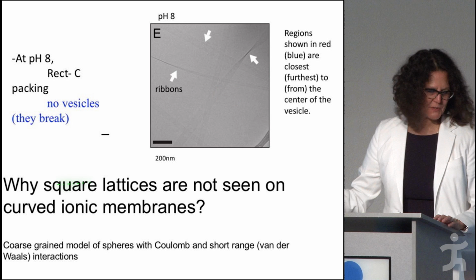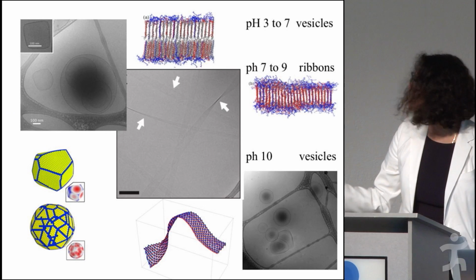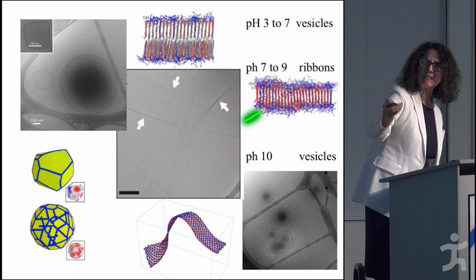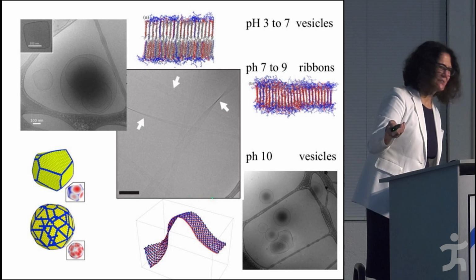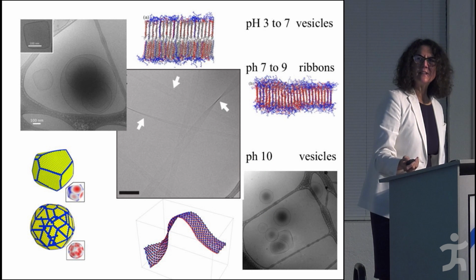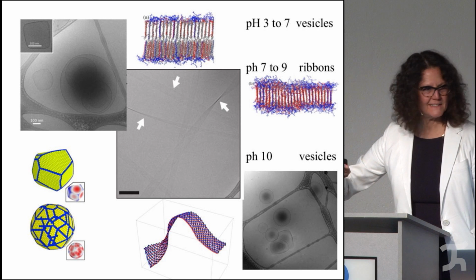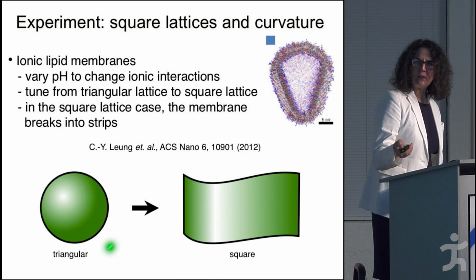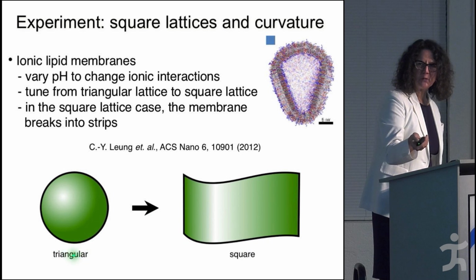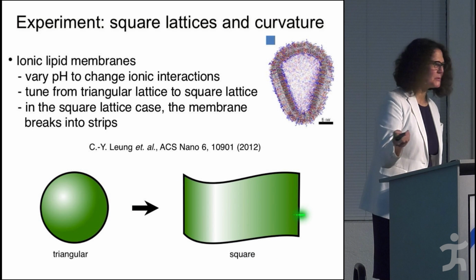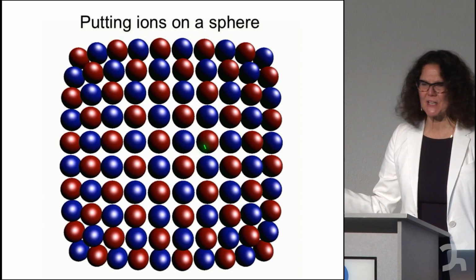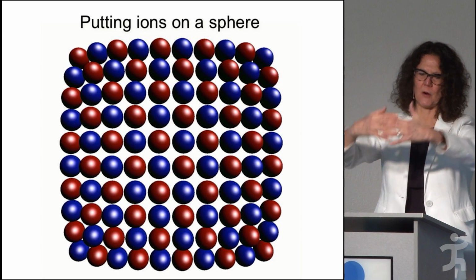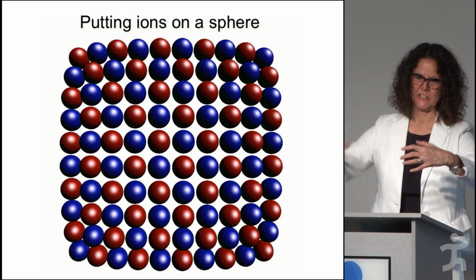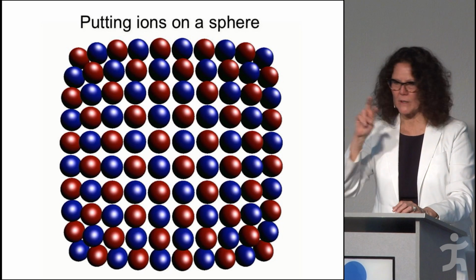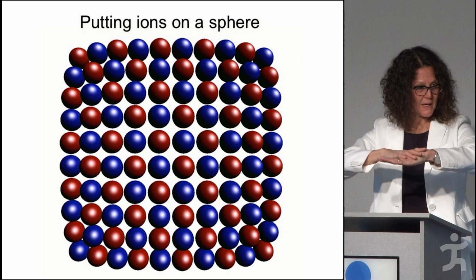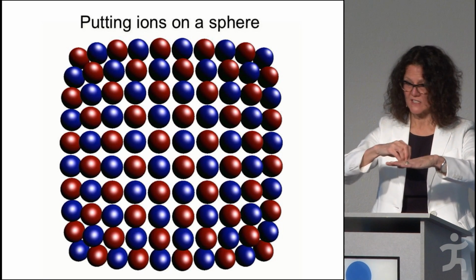And I'm just going to close by showing you the summary and the reason why we believe that with these rectangular C ribbons you cannot form closed structures. I'll show you very quickly. What will happen is that rectangular C looks more like a square lattice, right, as opposed to the other one. And so if you have a square lattice, why do you go from closed and triangular to square open? This is a simulation where you start with a big drop of water, say, or oil in water, and you put charges there, just fictitiously. And they are 1-to-1, so they have to form a square lattice. In a 1-to-1, all the nearest neighbors of the blue have to be red. So they have to be square.